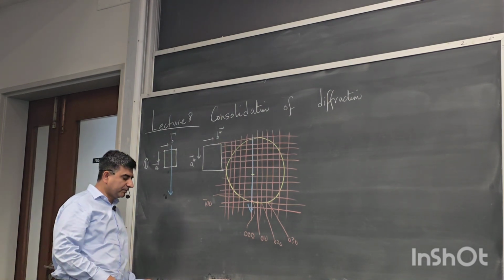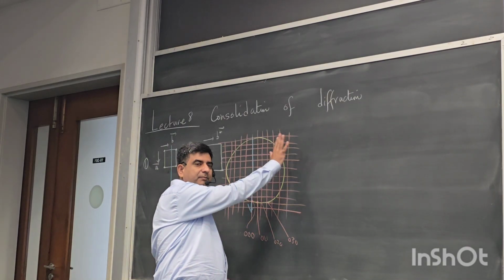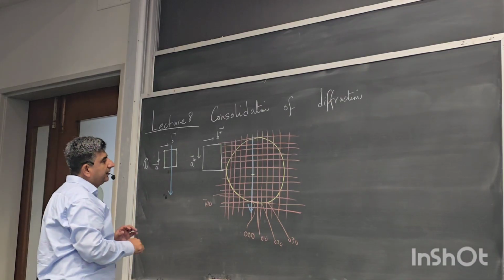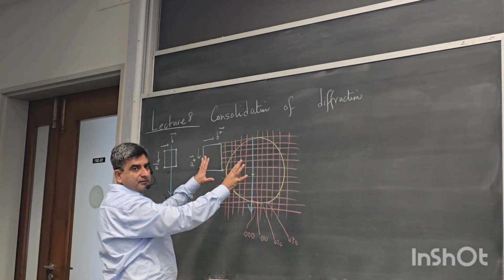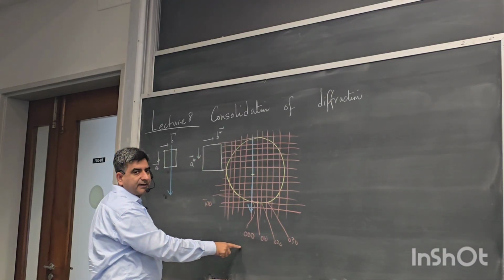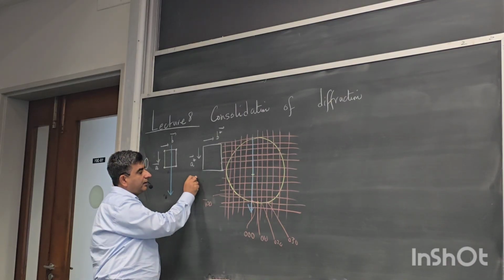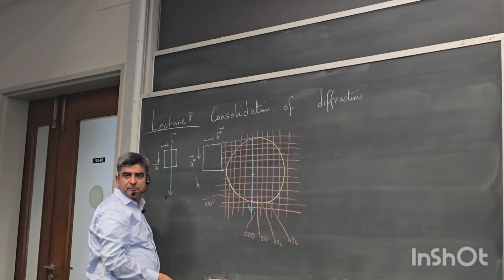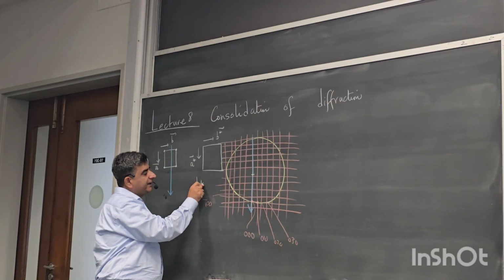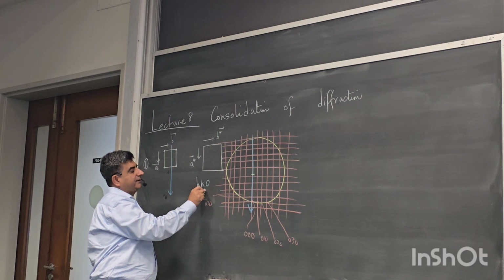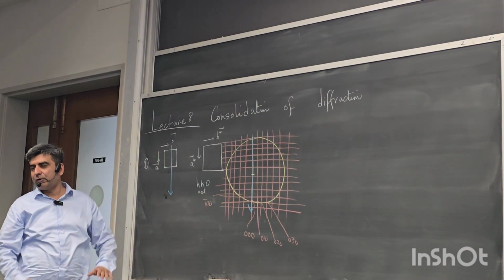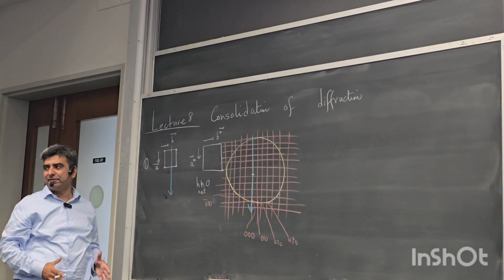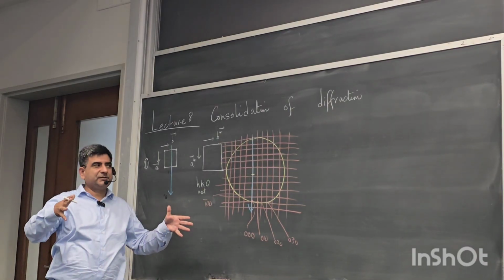And remember that at the moment we're looking at only one plane in the three-dimensional reciprocal space. So this is just one plane, and all of these reciprocal lattice points have their L value equal to 0. That's how we've drawn it. So this is the HK0 net in the reciprocal space. We'll also have an HK1 net, an HK2 net, an HK1 bar net, HK2 bar net, because the reciprocal space is three-dimensional.